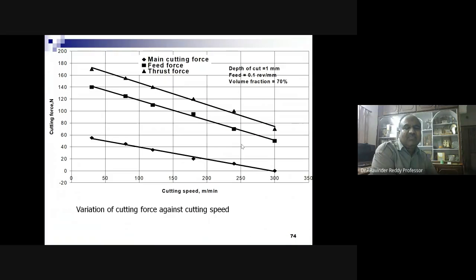When you measure cutting forces against cutting speed, it is a different kind of observation you can make. The main cutting force, feed force, and thrust force are in the order given here. With cutting speed, generally contact is increased and rubbing is there, so cutting force is supposed to increase, but surprisingly here the cutting forces are reduced. These experiments were conducted at depth of cut 1 mm, feed 0.1 mm per revolution, and volume fraction 70%.